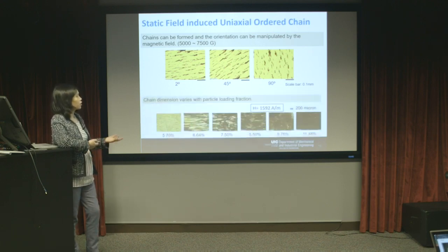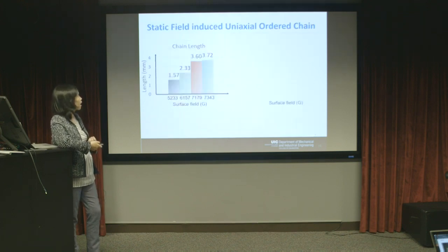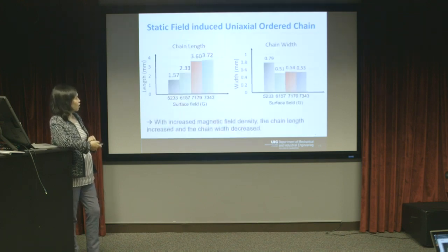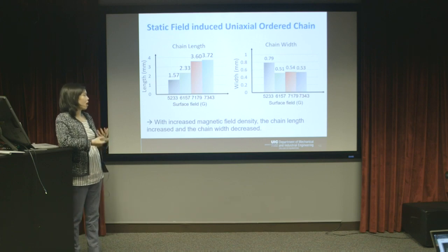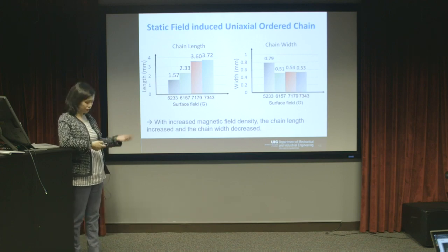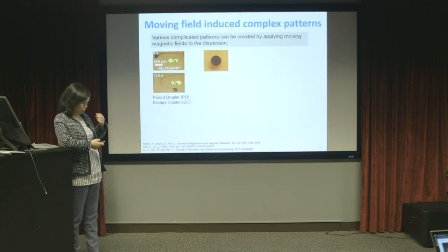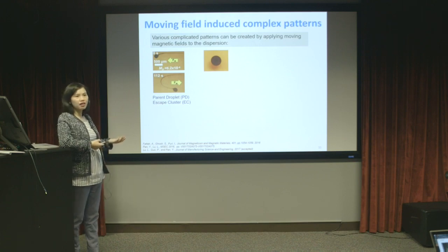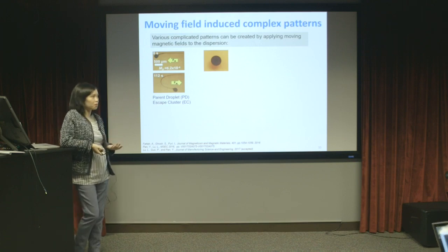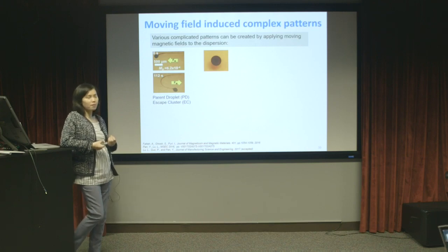And with different loading fractions of the particles, you can form chains with different sizes and different densities in the liquid resin as well. We found that with the magnetic field density increasing, we can increase the chain length. However, the chain widths will decrease. But we still need to do a more systematic and comprehensive statistical study about the relationship between the chain dimensions and the magnetic field strength.